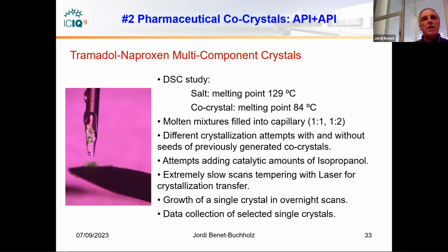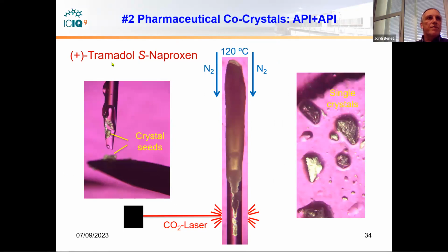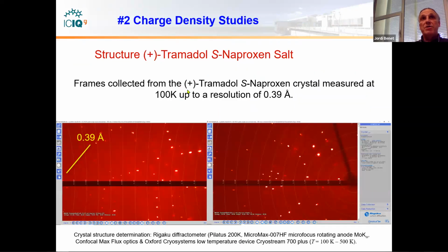And I was trying different methodologies. We were using solution crystallization, but also melting, using a CO2 laser on a diffractometer and making in situ crystallizations. Maybe you can see here. We fill a capillary with a melt of the solid. We add some seeds. We add catalytic amounts of isopropanol, and then, heating and warming with a controlled laser, we grow large crystals inside the capillary, so that after breaking the capillary, we can get large single crystals. Taking one of these large single crystals with X-ray diffraction, we could measure a high resolution data set.